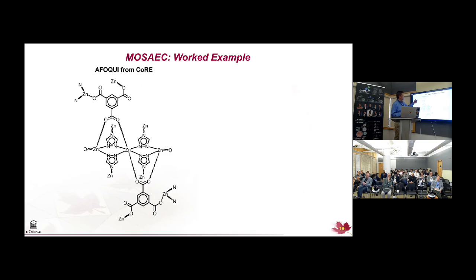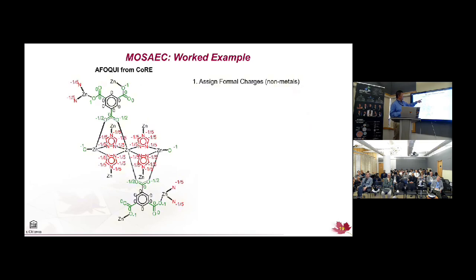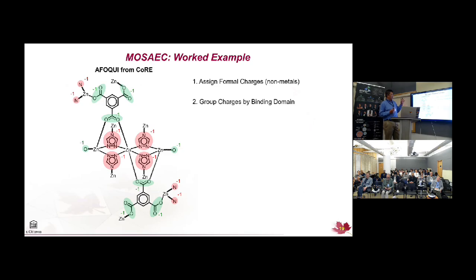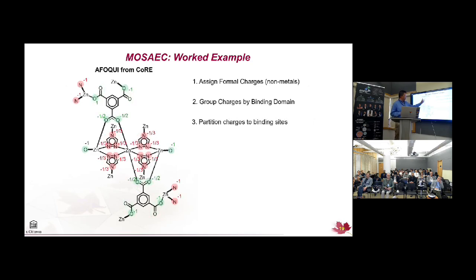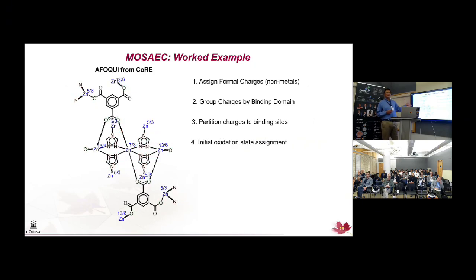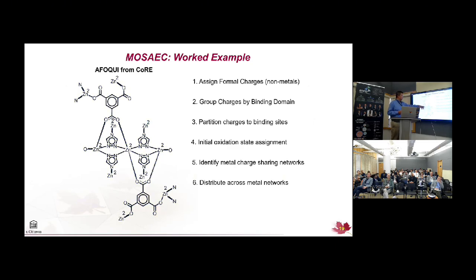So first you break all the metal bonds. Then you have to calculate all the oxidation states of all the nonmetals. That's the challenging part. You then group those charges into binding domains, and partition the charges to each metal in the binding domain. Then you get an initial oxidation state assignment, which is terrible. They're non-integer. But it turns out when you add the metal, this whole structure can share its charge. So you identify the charge sharing networks. They can share their charge, and then you end up with a good +2 oxidation state for zinc, which is what you expect, and this is a good structure.